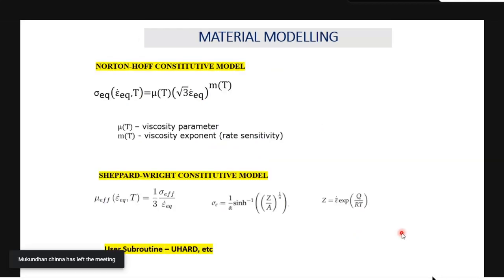The next material model is the Norton-Hoff constitutive model. This is another material behavior model. Here it is a function of the viscosity parameter and the viscosity exponent, and these are not direct values. You could not get a direct value of this, because this viscosity parameter will have a further lot of relationships, and each relationship has different parameters. With respect to time concerns, I'm not explaining much about that. Here the thing is they use this viscosity parameter and the viscosity exponent, which is nothing but the strain rate sensitivity.